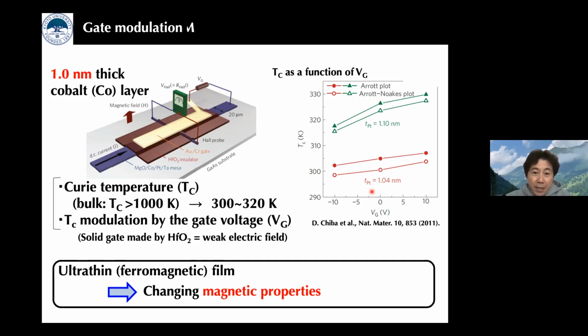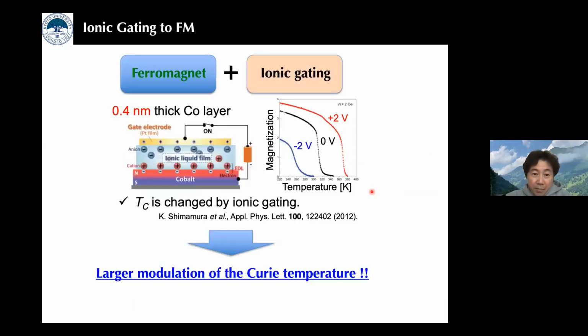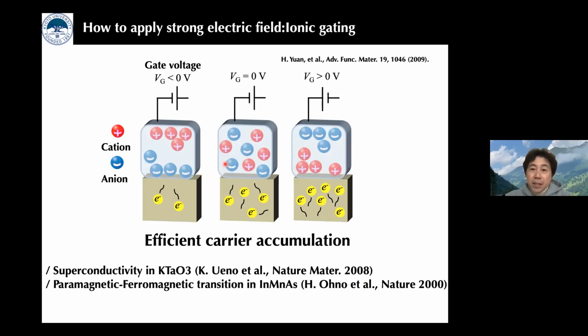Soon after that, the same group reported much more efficient magnetization control by gating, using the ionic liquid gating technique. In this slide, I explain the physics of ionic gating. First we prepare an ionic liquid and attach it on top of the solid. In the ionic liquid, cations and anions are uniformly dispersed, and of course under zero gate voltage nothing happens. However, when we apply a positive gate voltage, cations accumulate on the side opposite the gate electrode, and in consequence electrons accumulate on the top surface of the adjacent solid.